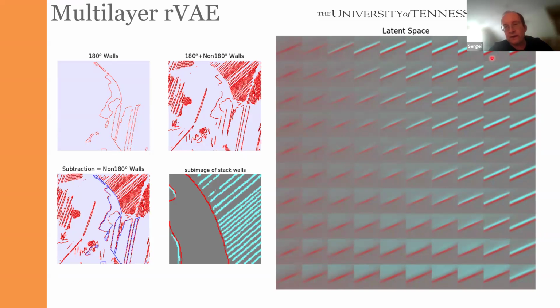So in this part of the latent space, you can see that 180-degree domain walls and non-180-degree domain walls are co-aligned and have equal intensity. That basically means that here these walls are pinned on each other, so they coincide.